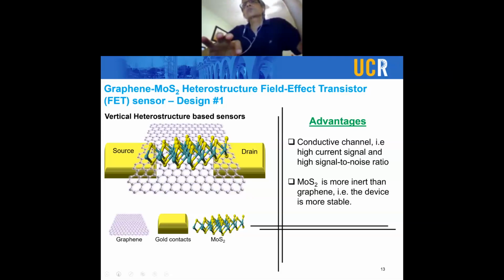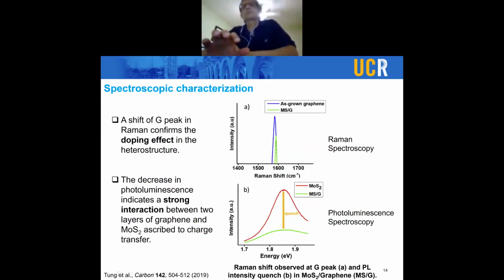So there are advantages of such heterostructure. As a chemical engineer, I was only looking for a good sensing. But before we venture into sensing, we need to make sure we do the characterization of material. We characterized the heterostructure and compared the properties of the pristine materials, which is pristine MoS2 and pristine graphene, versus heterostructure, and concluded that we did indeed have a heterostructure in which the two materials were interacting with one another. And those interactions were observed through the shift of the G band of the graphene and the quenching of the photoluminescence shown in figure B. Figure A is the Raman. And both of these confirm that, in fact, we are having a good interaction, and they were working in tandem.